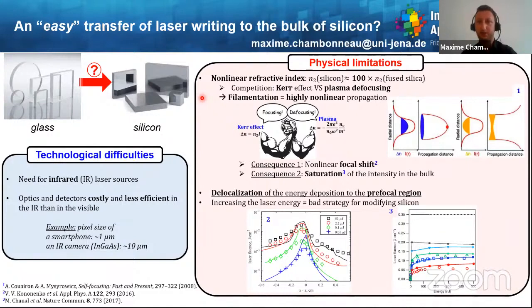And this filamentation regime has two major consequences. First of all, there will be a nonlinear focal shift, as you can see here on the bottom left. For low pulse energies, the beam is focused here. And then when you increase the energy, the focus shifts upstream of the laser. The second consequence is a saturation of the intensity inside the bulk, which is shown here on the right. So when you increase the energy, well, the laser fluence, so the real deposited energy inside silicon, is limited and saturated.